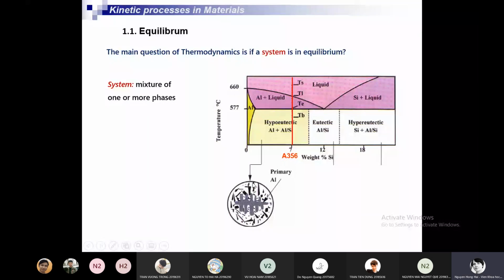And we have the primary aluminum plus eutectic. The eutectic is the silicon in dark embedded in the aluminum like this. Okay, so here we have the primary aluminum and we have silicon, eutectic silicon. It's the chemical composition, hypoeutectic. Mainly we have, for example, 7% of silicon for this alloy A356. We have this microstructure.